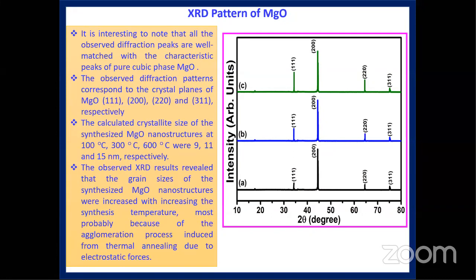And we can also calculate the grain size of this MgO nanostructure. The grain size calculated for 100 degrees Celsius is 9 nanometers, for 300 degrees Celsius is 11 nanometers, and for 600 degrees Celsius is 15 nanometers. You can see that when the synthesis temperature is increased, the grain size also increases. The reason is the agglomeration process induced in the material, and also electrostatic force involved. So due to the thermal energy, the grain size increases.